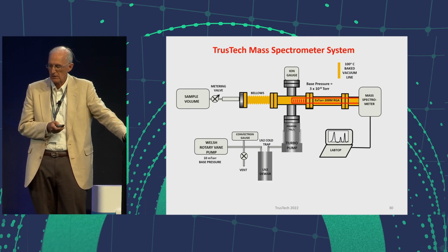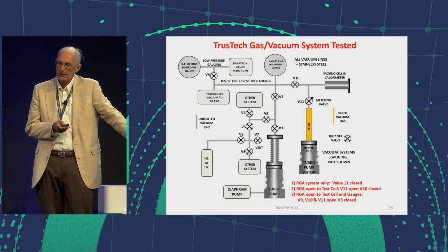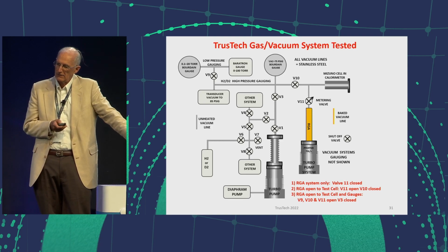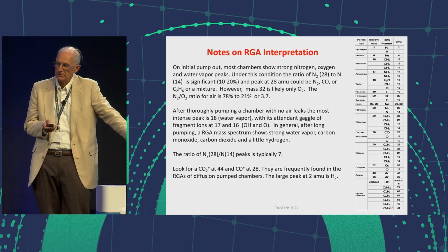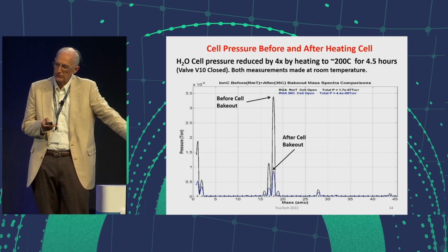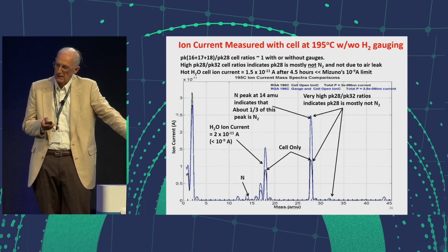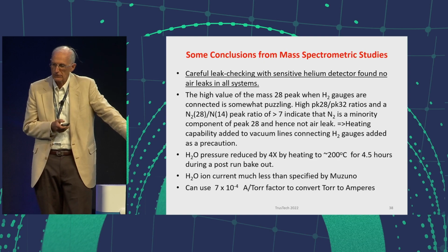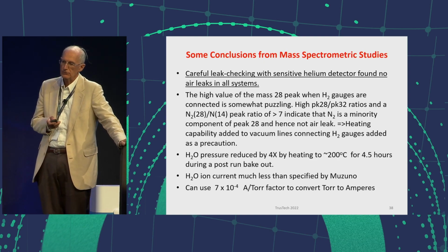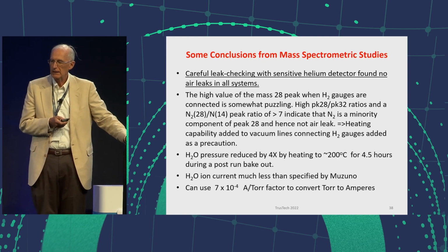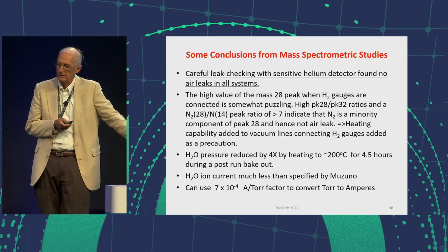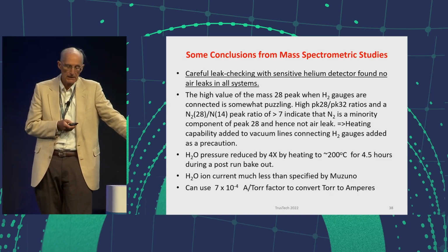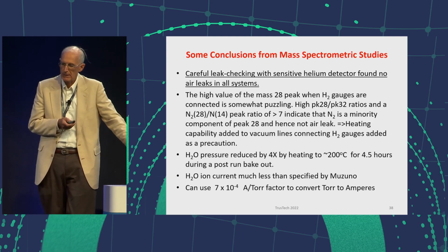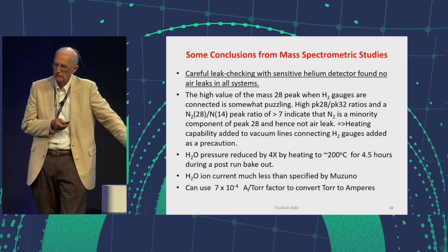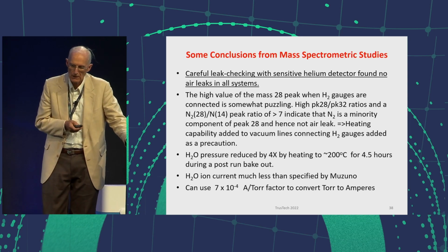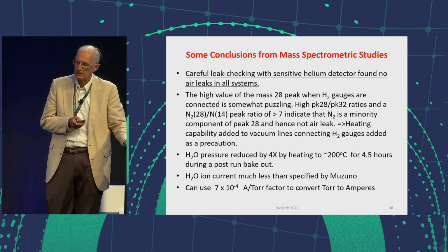This is my mass spectrometer system. This is the vacuum system, how it was set up to use. And then I have a lot of slides on interpretation, the results, which you can look at. But getting to the results, I'll just point out two things. At the top, this system allowed a careful leak detection with a helium leak detector, which indicated it was tight. And second from the bottom, the H2O ion current was much less than specified by Mizuno. So I assume I was meeting all his criteria in these measurements.